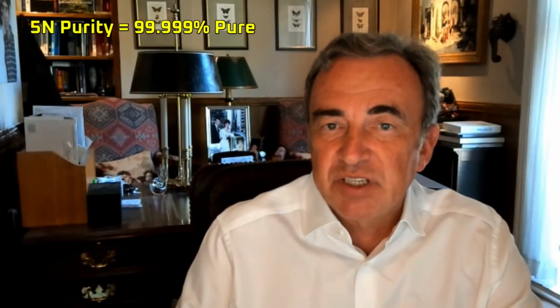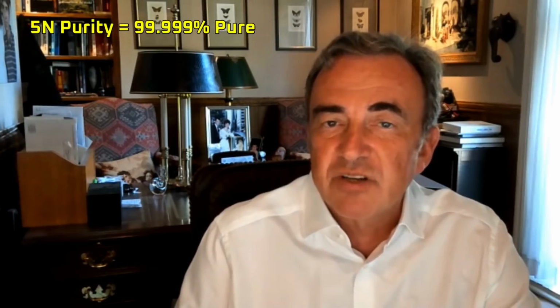Now, the other two pieces that are important: the cheaper the graphite, the cheaper Sinanode, because we don't buy the graphite. Okay, that's the first piece. So if our customer finds a cheaper source of graphite or wants to blend natural graphite and synthetic graphite, we can grow nanowires on any kind of graphite, including natural graphite. So they have more flexibility, and most of them end up blending different graphite from different suppliers anyhow. Now, the other piece is, how do we do the processing? And here's the beauty of it. First, the silane we use has 5N purity, so we don't need to remove any impurities. It's already pure enough.